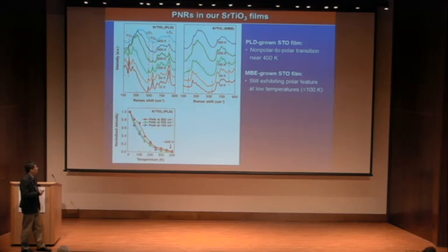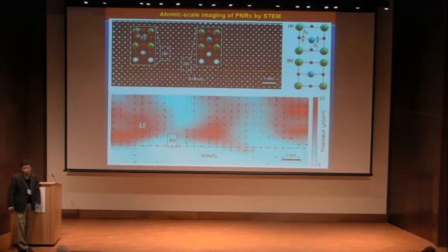And when you do that and look at those same films, they are much weaker, and there's no existence of those Raman peaks, and that means there are no nanopolar regions at room temperature, or still, at room temperature, very, very tiny ones. So you can see much stronger nanopolar regions due to the strontium-titanium anti-site ions, creating nanopolar regions. So we look at this one by microscopy, STEM work.